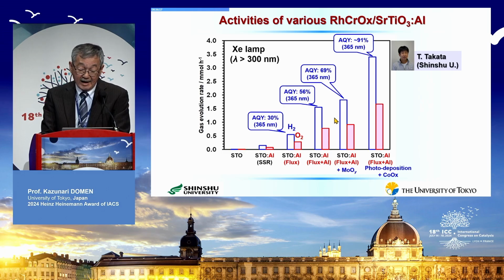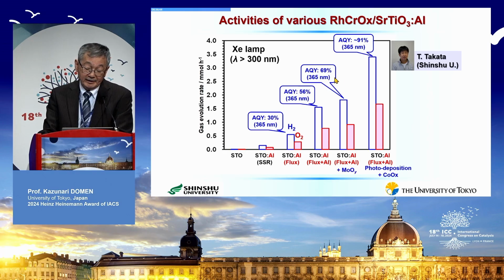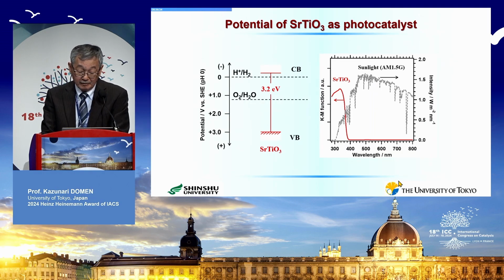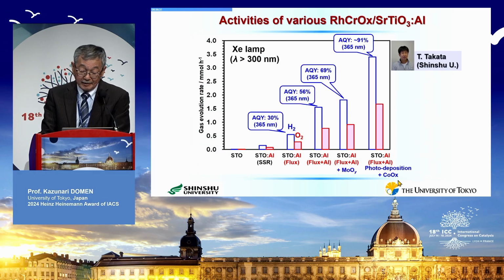This is a very high quantum efficiency already at a wavelength which is included in sunlight. After that, we added a co-catalyst for O2 evolution in addition to this hydrogen evolution co-catalyst. At first, we found that when we used molybdenum oxide, the apparent quantum yield increased to almost 70%. But after some period, we realized that when we used cobalt oxide, and all the metallic components of this co-catalyst, I mean the cobalt, rhodium and chromium, were photodeposited, the apparent quantum yield exceeded 90%. And this was actually developed by Professor Takata at Shinshu University. This is an extremely high quantum efficiency. So I would like to discuss this type of photocatalyst in a little more detail.